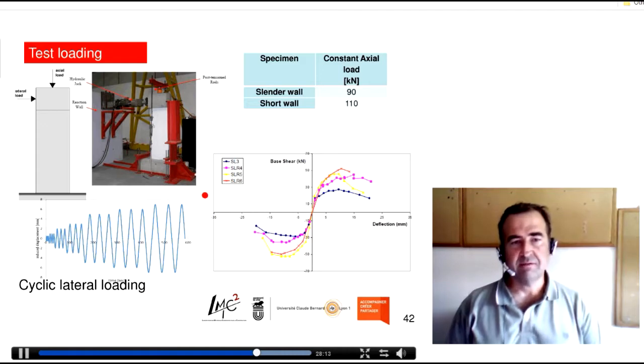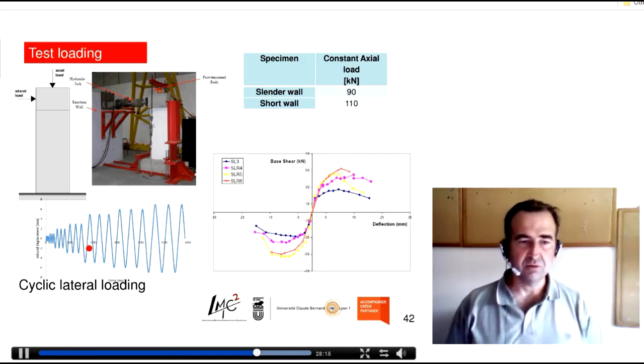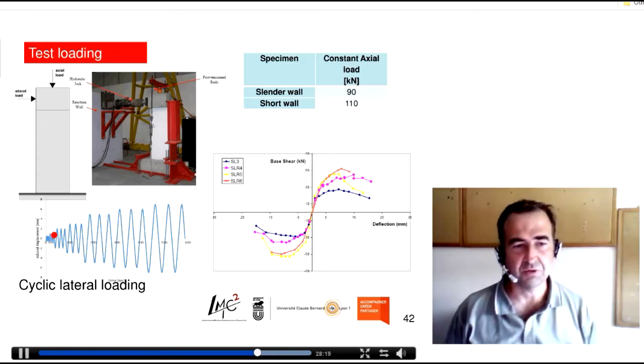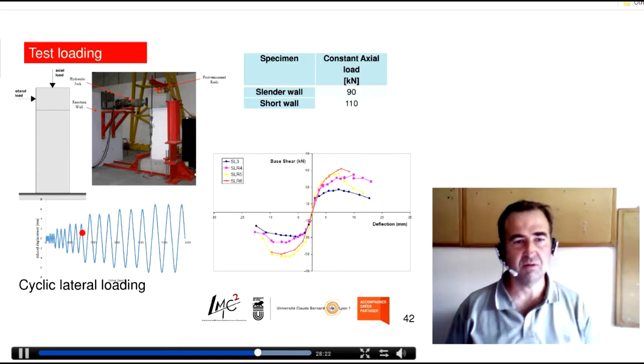Then, the testing device is already well known. The loading procedure is quite usual for this kind of test. We increase progressively the displacement. The load is displacement controlled with a speed of 100 millimeters per minute. Then a vertical load is applied, a hydraulic jack load to control the vertical one, and a horizontal load is applied cyclically. Then these are the results we have typically if we look only at the maximal load and displacement for each level of hysteresis curve.